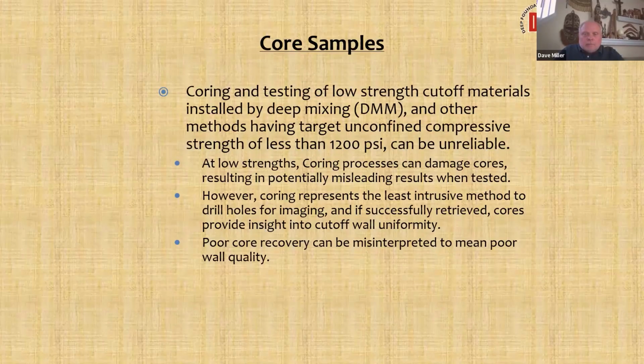Okay. So the core samples, coring and testing of low strength cutoff materials installed by deep mixing and other methods having targeted unconfined compressive strength of less than 1200 psi can be unreliable. And that's because the matrix is so relatively weak. Okay. So the coring process can damage the cores, and this can lead to misleading results and misunderstandings on the project. But it's also the least intrusive method to drill holes for imaging. And if you get good cores, they can provide an insight of the uniformity of the material. And poor core recovery can be misinterpreted and mean poor wall quality.